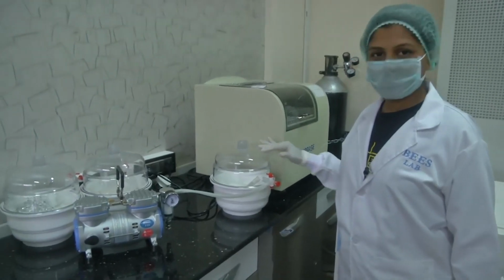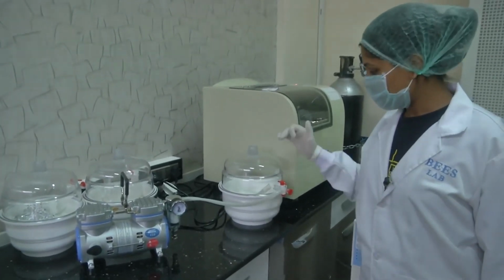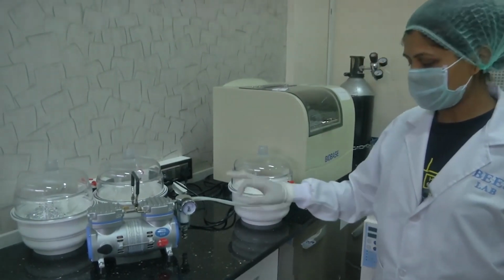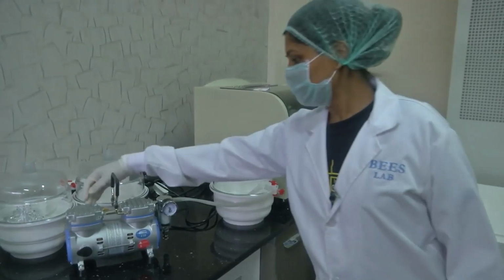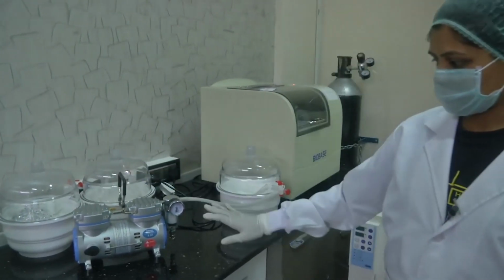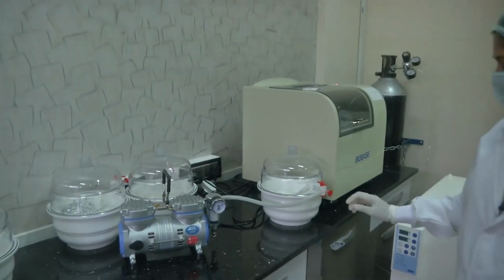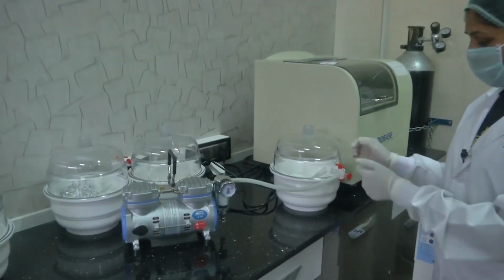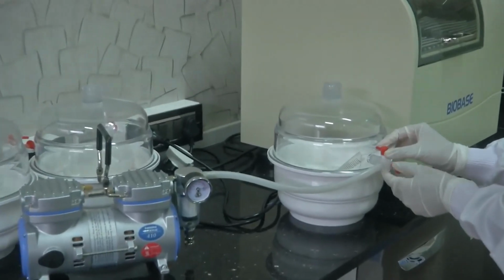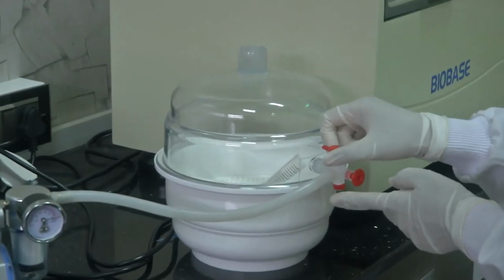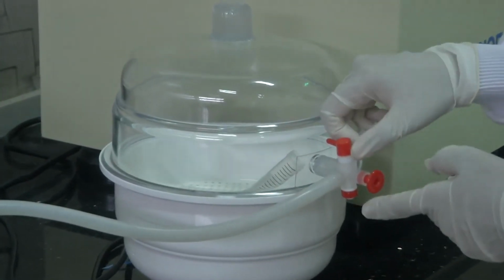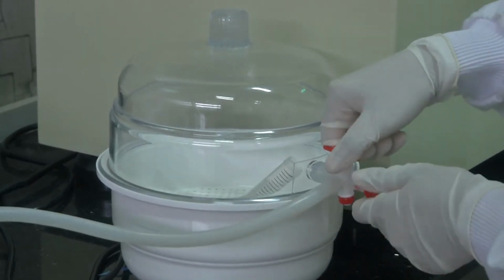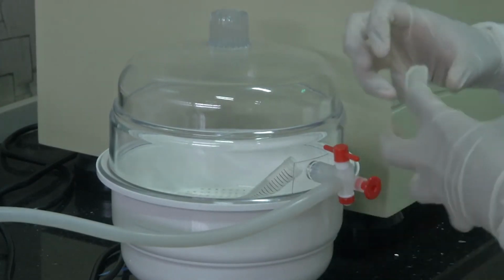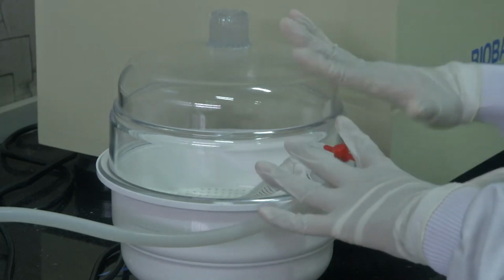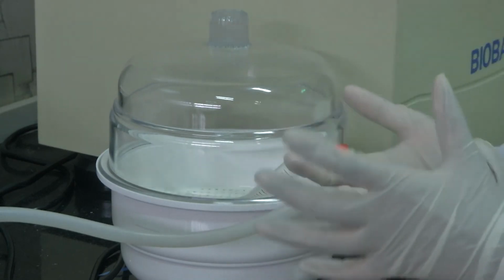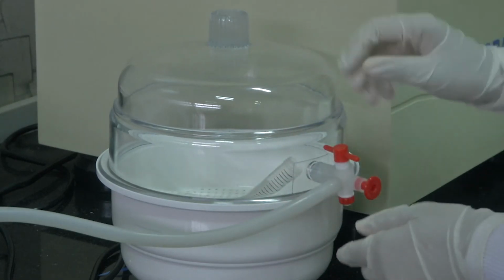Having given around 15 minutes of time for desiccation, now that there are no more air bubbles, what I am going to do is switch off the pump, and then you have to slowly release this valve here, because if this knob is turned very quickly, a lot of air gushes inside the chamber, and that can again form air bubbles in the mixture. So, that is not what we want.